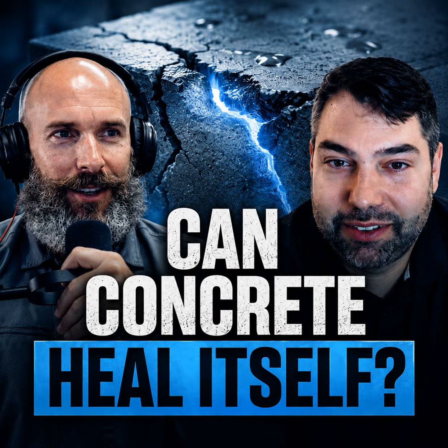Uh-huh. We actually started as a repair company. So back in 1969 is when we were founded, but we started as more of a coating system for existing structures. So if you have an existing concrete wall and you want to waterproof it or repair it, what you can do is basically you need to make it clean. You need to power wash it. You need to get it down to a CSP3, which is like an 80 grit sandpaper. And there's chips the Concrete Repair Institute has. You can buy the chips, and they'll tell you what the feeling should be and the look. But really a power washer tends to do it with the concrete.